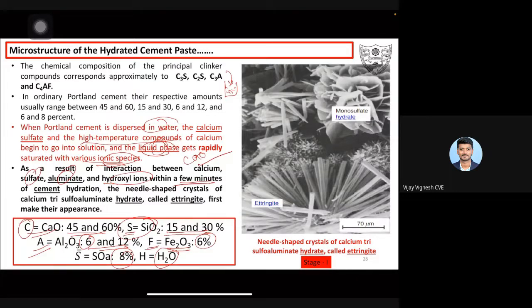within a few minutes of hydration, adding the water, within a few minutes, the cement hydration, the needle-shaped crystals of calcium trisulfoaluminate hydrate, called ettringite. So within a few minutes, you can see in the scanning electron microscope needle-like structures. Like this is a needle-like structure. Around 70 micrometers, you can see needle-like structures. So needle-like structures are present in the hydrated cement paste. We can call it as ettringite. This is a primary hydration process. This is called primary ettringite. Okay. So this name is called ettringite.